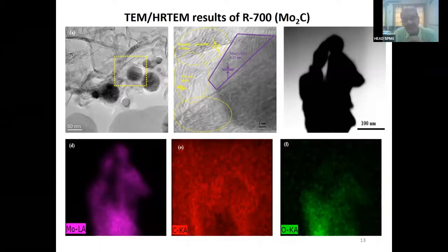From these structural features, what we could conclude, for catalytic application I am talking about, is that it's not important that you get a very good molybdenum carbide. It's important that you have some hybrid type of structure which may comprise molybdenum, carbon, and also some leftover oxygen. It provides a very good platform for the capacitance application in this case, which I will be talking about at a later stage.